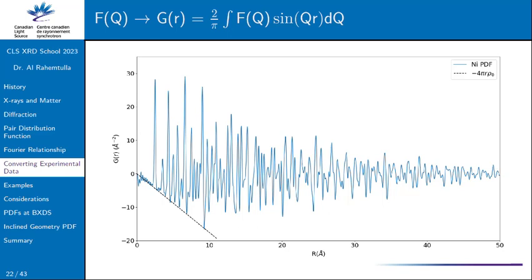Yeah, that's really the total PDF, which includes all the atom pairs. On the next slide, the partial PDF is for just one type of atom, looking at all the other types of atoms. The signal also dies off very quickly. It'll tell you something about the nearest neighbors and maybe a little bit about the second or third nearest neighbors, but nothing about the long range.